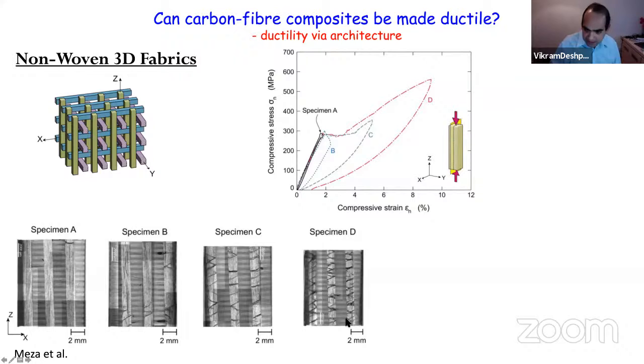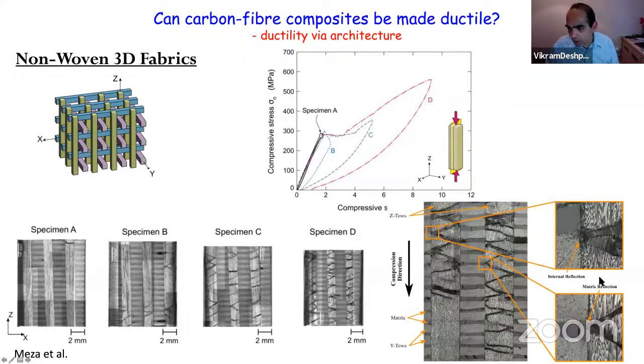Now, this is really interesting because if you look at it more closely, you see that this is a traditional kink band in the sense analyzed by Budiansky and Fleck and many others, basically, that you can see that these fibers have kinked here. But in normal carbon fiber composites, you get a kink, and it sort of completely traverses the specimen, and you get an unstable failure occurring. But here, what has happened is that you're getting the kinks zigzagging. Basically, they reflect inside the tows, and you're getting a rather stable situation.